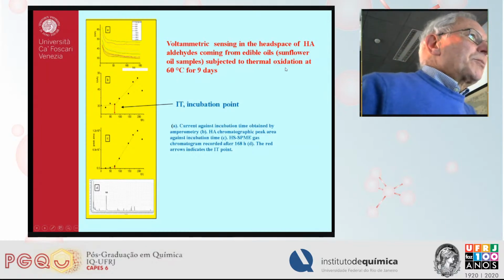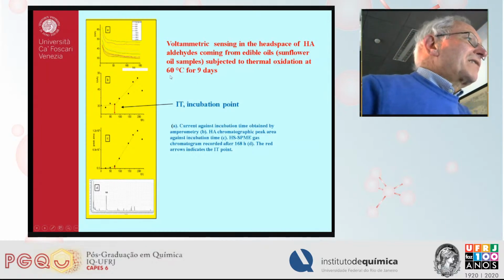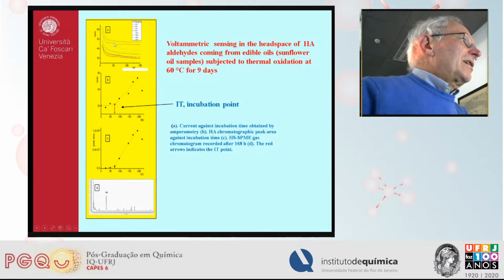We followed this process at 60 degrees centigrade for 9 days. So these are typical chronoamperograms we obtained, and this is the result concerning the evaluation of the limiting current against time. This measurement referred to the amperometric measurement.